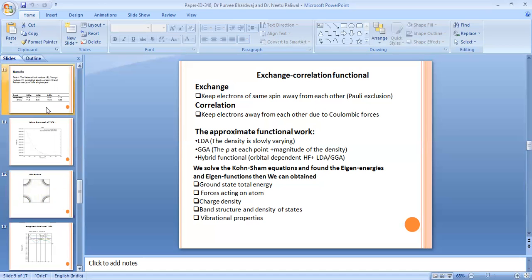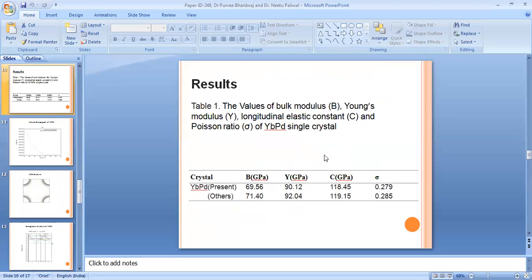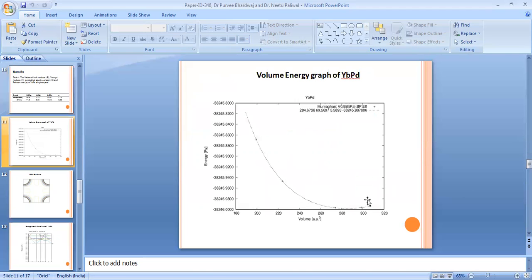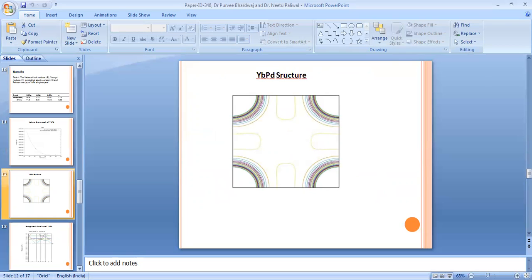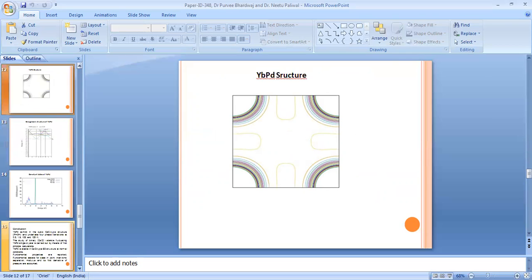Using these calculations, we have computed some results for the YbPd single crystal. The values we have calculated are bulk modulus, Young's modulus, longitudinal elastic constant, and Poisson ratio of YbPd single crystal. We have compared our results with available data, and it is clearly seen that our values are in good agreement with available theoretical results. The volume-energy graph of YbPd has been plotted with volume and energy in this graph. The basic structure of YbPd is shown in this figure.